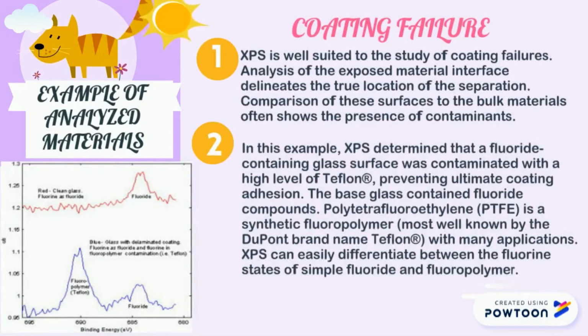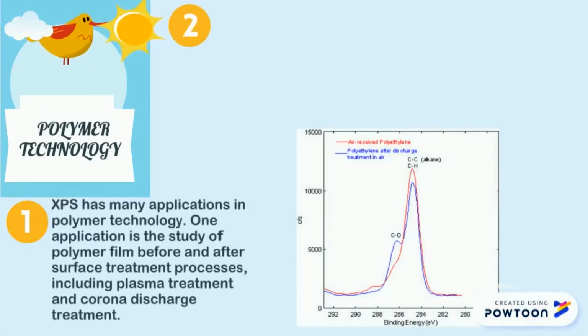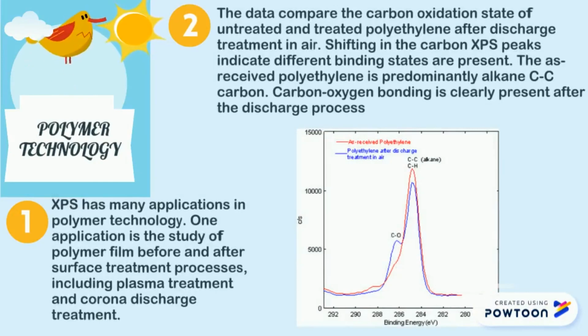In these examples, XPS determined that a fluoride-containing glass surface was contaminated with a high level of Teflon, preventing ultimate coating adhesion. The base glass contained a fluoride compound. Polytetrafluoroethylene is a synthetic fluoropolymer, most well known by the DuPont brand name Teflon, with many applications. XPS can easily differentiate between the fluorine state of a simple fluoride and a polymer. XPS has many applications in polymer technology.